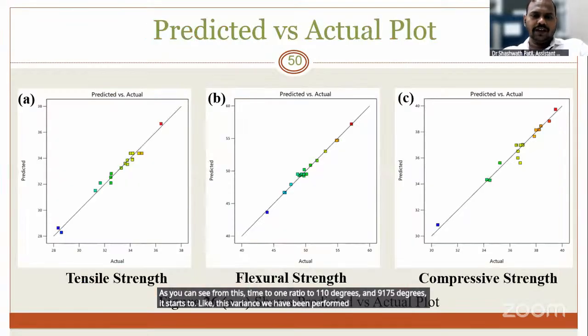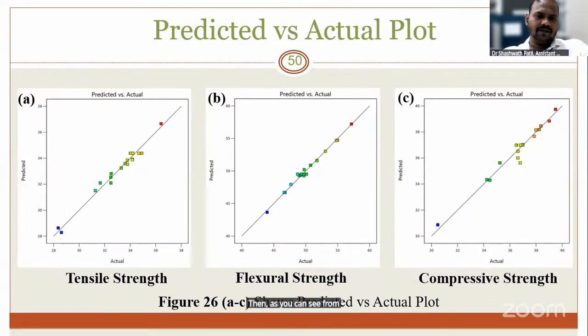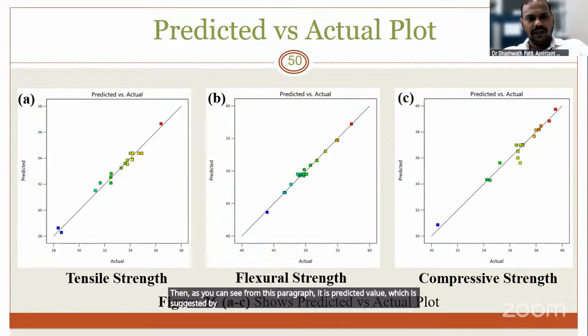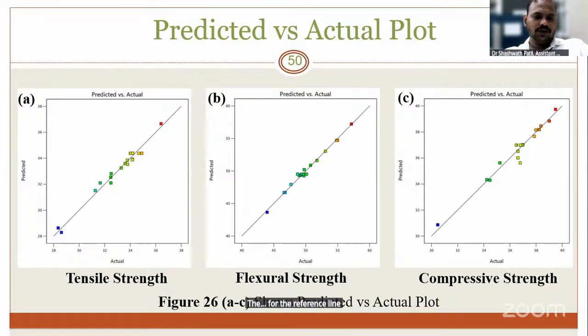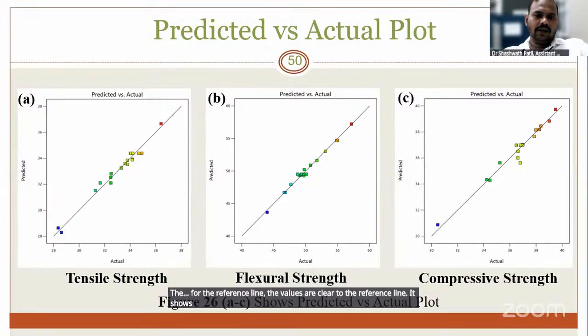Then, in this graph, the predicted value is suggested by the RSM software, and the actual value is what we attained from our experimental results. As you can see from these three responses, the values are near the reference line. It shows that our experimental values are near the predicted values.